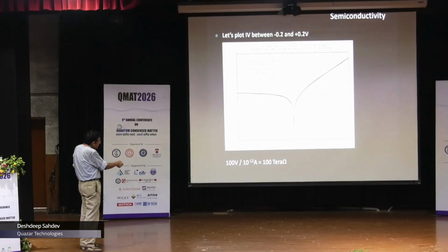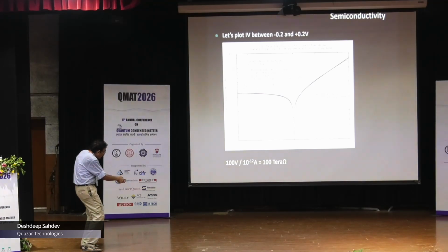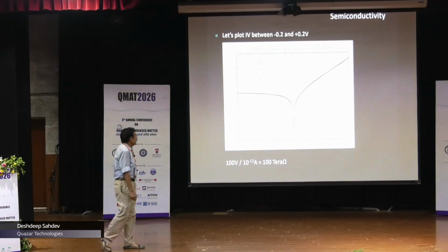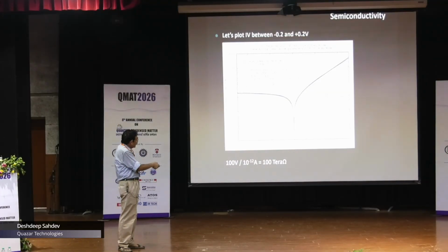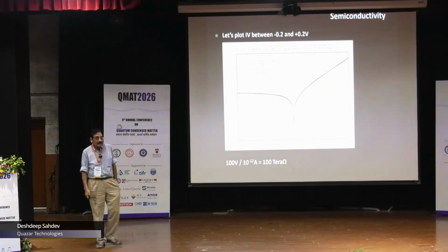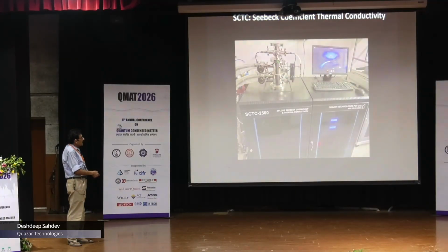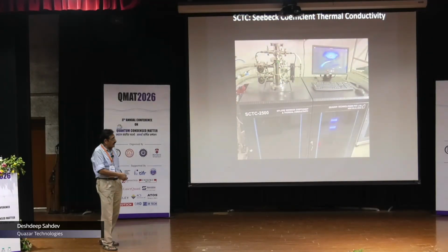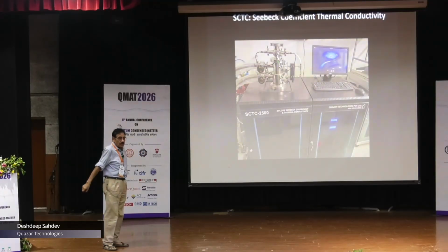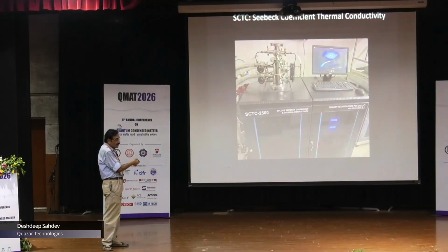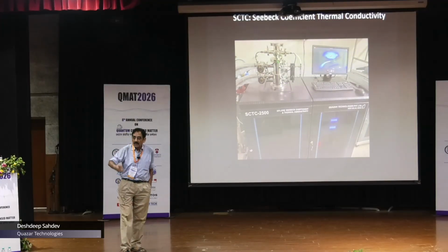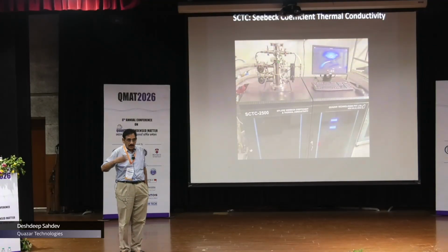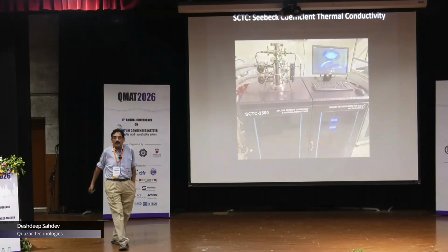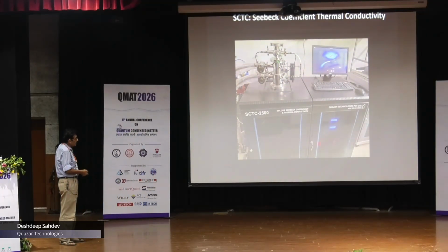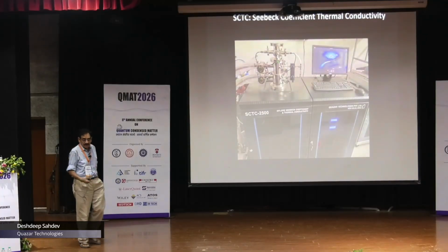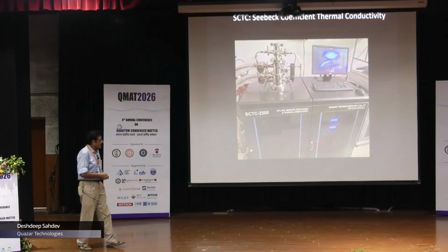And this one, of course, can be fit almost perfectly. So the red line and the red dots that you see are experimental data, and the blue line is a fit to the Shockley ideal diode equation, all right? And then we've done stuff in magnetism, and we've now gotten into the thermal properties. So we built a Seebeck coefficient and thermal conductivity system with which we can get the whole figure of merit out and so on. So anyone who's into thermopower can use this, and this one now is 80 to 800 Kelvin, all right? It goes up to 500 degrees centigrade.